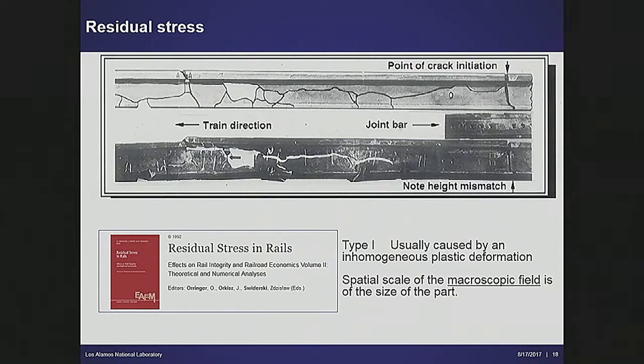This was a piece of rail that in the 80s was the source of a problem in Texas. Trains had run over it for many years. And then they found a small problem with it, and they came in with a repair, right? And so in the repair, instead of the top layer being flat, there was a small step in it. Remember, this is rail that had been in service for many years. They did the repair, there was a step. When the next train came along, a crack propagated from the step, but instead of being limited to the surface, it made it down into what was called the web.